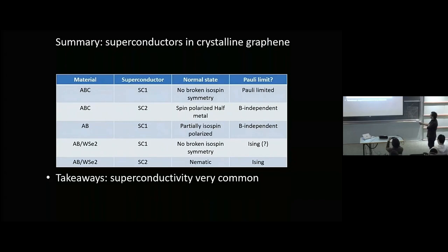There are some that have no broken isospin symmetry in the normal state. Those can be Pauli limited, typically in ABC. They're Ising, it looks like, in the spin-orbit version. There are those that come from spin-polarized half metals, and those are magnetic field independent, so they look indeed like spin-triplet superconductors. They're really just a spin-polarized ground state. And there are those that come from states that seem to be nematic in their normal state.